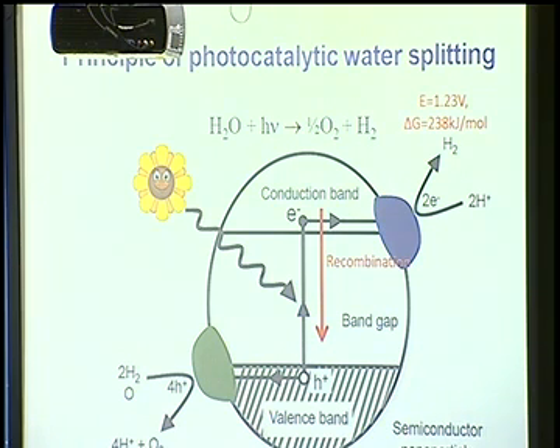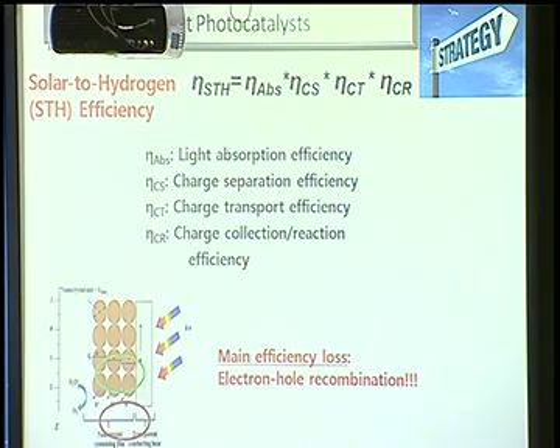When light of sufficient energy falls on semiconductor nanoparticles, there is excitation of an electron from the valence band to the conduction band. At the valence band side, water is oxidized to O2 gas, and at the conduction band the free electron reduces protons to H2 gas. But the most important factor here is recombination, because the excited electron is quite unstable and tends to recombine with the hole, and this recombination always decreases the efficiency of a photocatalyst.